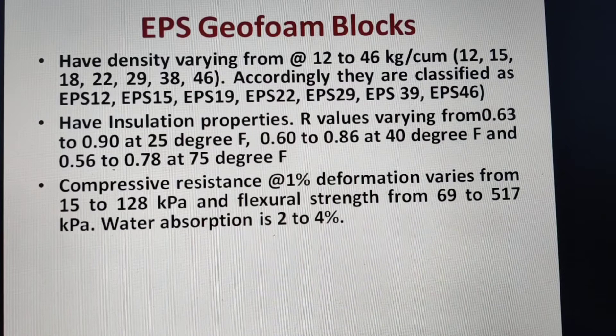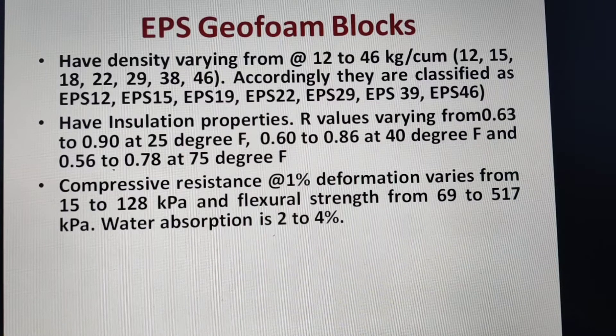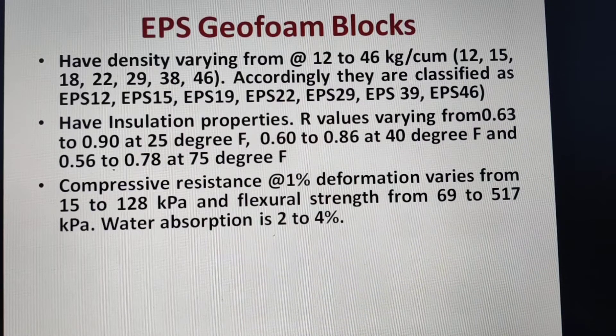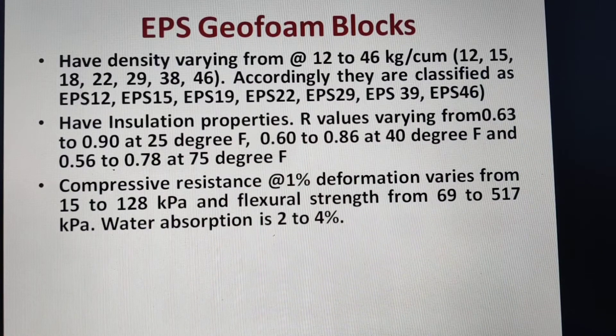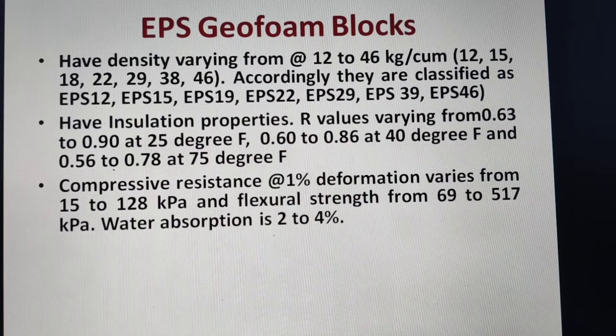They have good insulation properties. R-values vary from 0.63 to 0.9 at 25°F, 0.60 to 0.86 at 40°F, and 0.56 to 0.78 at 75°F for a particular brand. Compressive resistance at 1% deformation varies from 15 to 128 kPa, and flexural strength from 69 to 517 kPa.